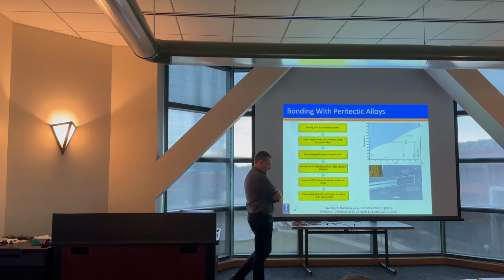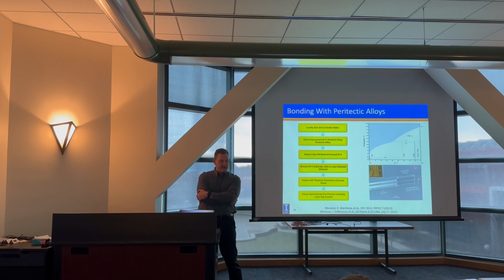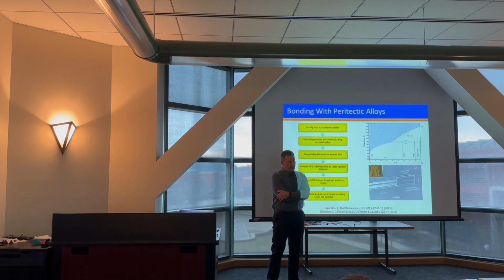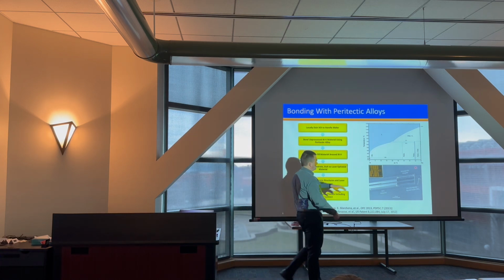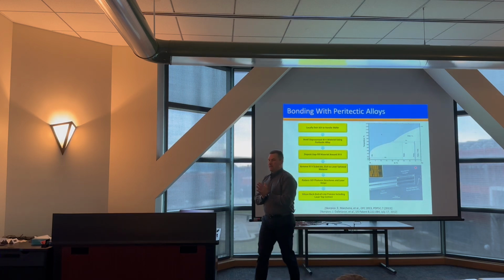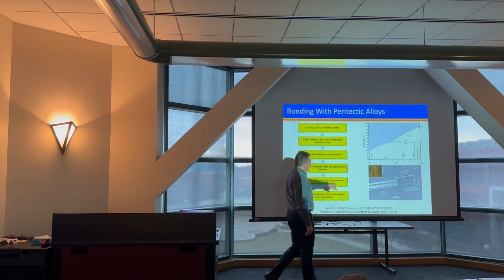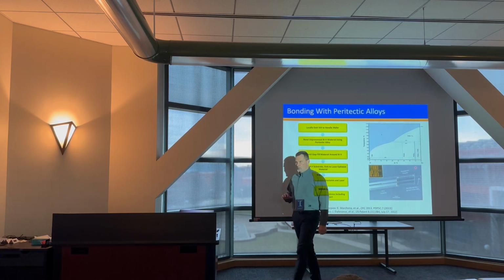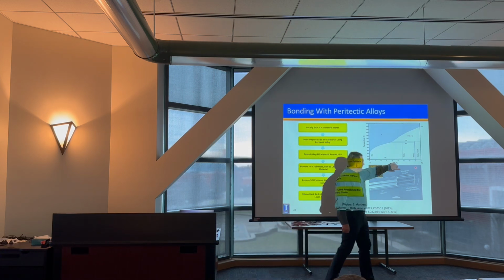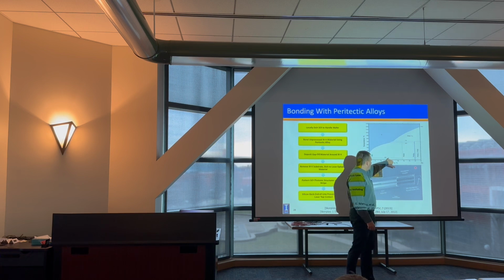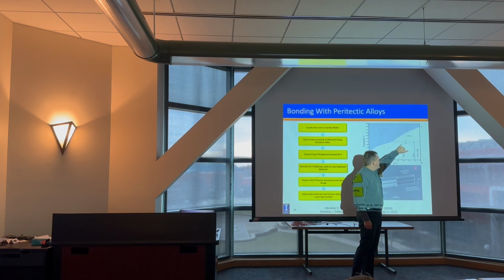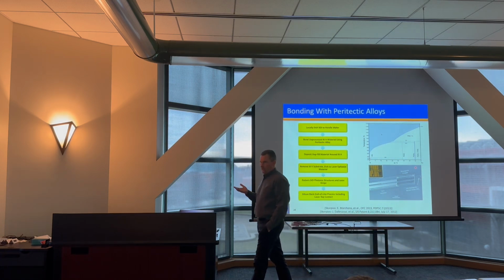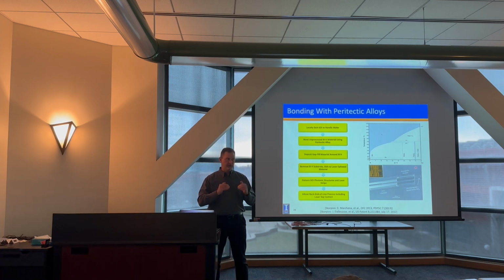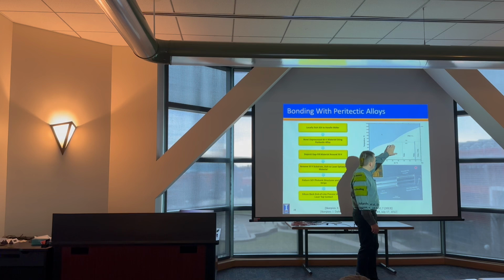And then there's another interesting type of system that people have used, and that's bonding using a peritectic alloy. For example, indium palladium is one system that has the capability of melting at a low temperature, okay? If I have liquid indium in contact with the palladium layer, there's going to be a reaction between those, and I'm going to form palladium-3 indium-7, and that, as opposed to having a melting temperature at the temperature of the indium, is going to have a melting temperature of over 600 degrees, almost 700 degrees. So I can bond at a low temperature if my layers are thin enough, and then if I fully consume my indium and my palladium, that bond is going to be stable up to almost 700 degrees.